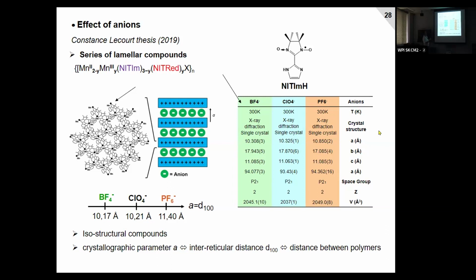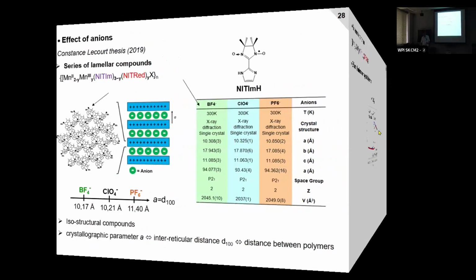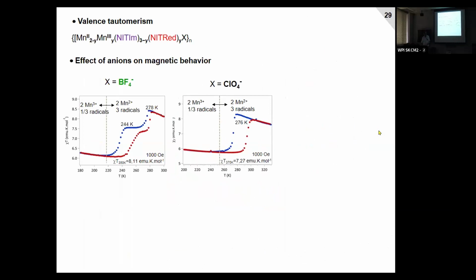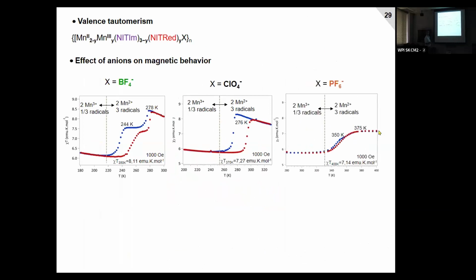So in that case, Yuta was able to get single crystals, and we were able to solve the crystal structure with BF4 and PF6. So you can see that the crystal parameters are very close. Again, we have P21 in Sessoli. And in that case, we still have valence tautomerism, but we have different behavior. So here, the behavior of the perchlorate I showed you before, and now with BF4 and PF6. If you look, for both we have the same transition, but in 2 steps. The first step, the second step.